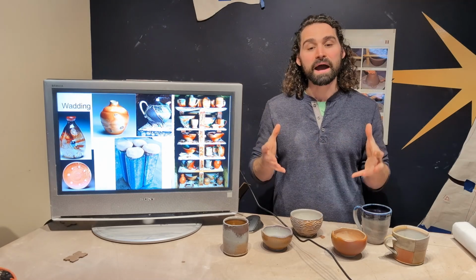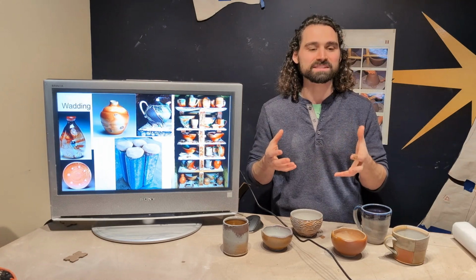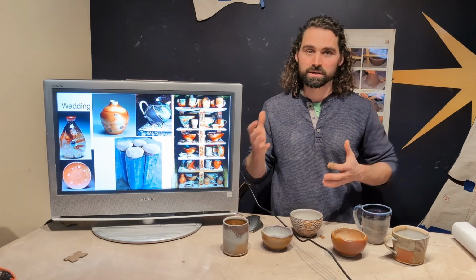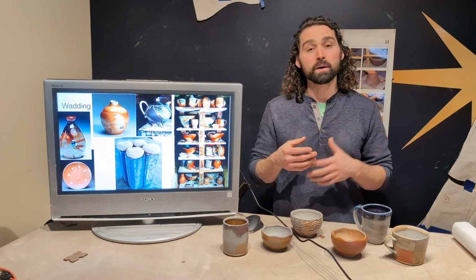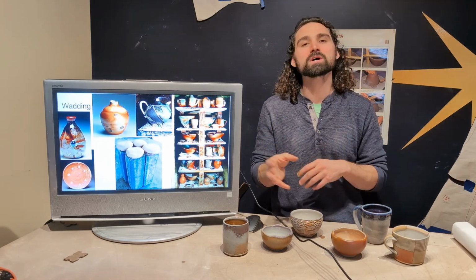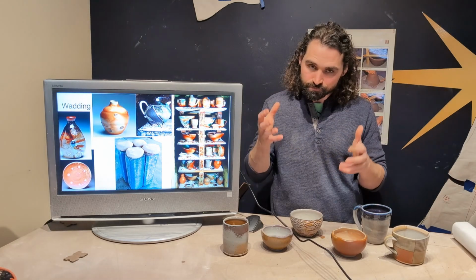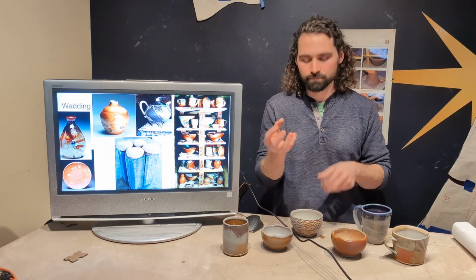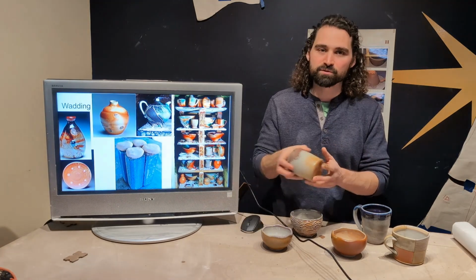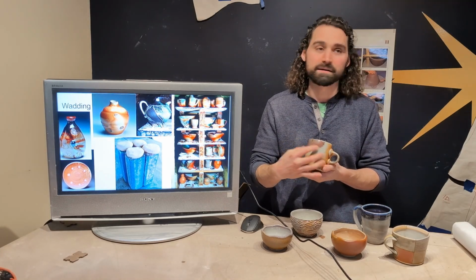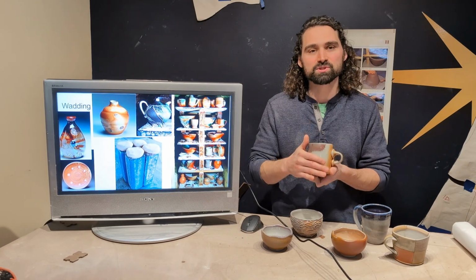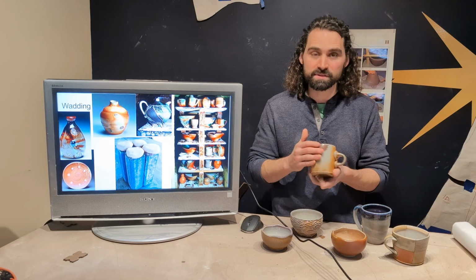Wadding. So what happens in these atmospheric kilns where you're adding some sort of sodium into them? In this firing in particular, most soda firings, we're adding sodium carbonate, washing soda into the kiln. In wood firings, the wood ash acts as this kind of extra atmospheric change, but also some wood fires will put salt in their kilns. That extra sodium in the kiln bonds with the surface of your piece, and it draws the silica and iron to the surface and creates a sodium silicate glass on your pieces.